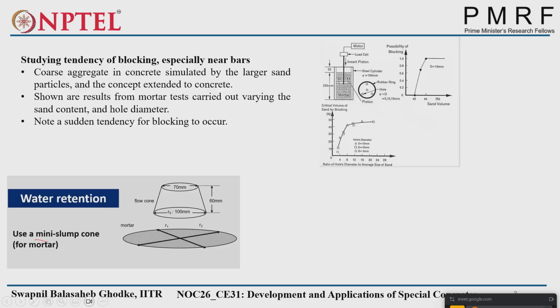This is what we call the mini slump cone. It has a top diameter of 70 mm, a bottom diameter of 100 mm, and a height of 60 mm. We'll do the same procedure. We'll put it on this table or platform at the center. Without compaction, we'll pour the material into it, and then lift the mini slump cone, and the concrete will flow automatically over the surface. Then we'll measure the larger diameter first, and then another diameter perpendicular to that one, and we'll get the average of those diameters.